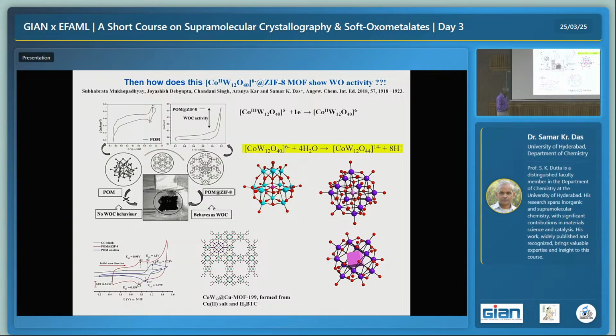Recently we put the same cluster in another MOF, copper MOF-199. It is BTC, benzene tricarboxylic acid, a very well known MOP. So in this case, we got a single crystal structure, of course with very high symmetry, and we could locate the cluster inside. In the earlier study we could not get a single crystal, only PXRD.